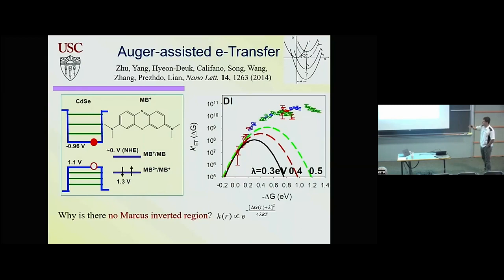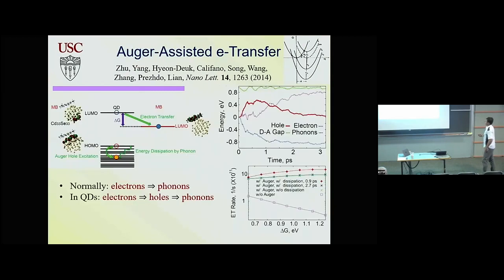So what is the explanation? This is no longer a molecule, but it is not bulk material either. It's a quantum dot where you have a strong high density of states and strong interactions between charges. So the energy is actually deposited into the hole. You have an electron going from the quantum dot to the molecule, but the energy is not going to vibration. So this Marcus model, assuming that the energy goes to vibration, doesn't really apply, because the energy goes to the hole, and then the hole has a high density of states, and that relaxes very fast to the edge. Within maybe 3 picoseconds, you don't even know that the hole was ever excited because everything relaxes to the final state. But this intermediate Auger-like process basically governs charge transfer from the quantum dot to the molecule.